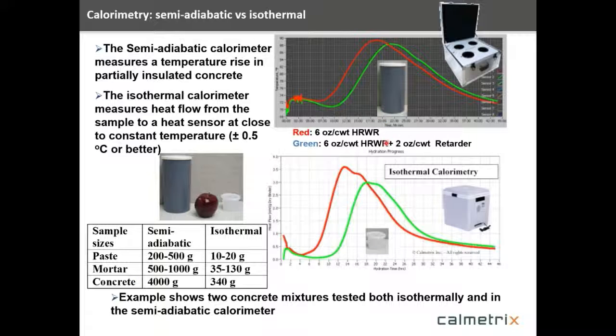Here is an illustration of the fact that the curves look very similar, but again, we're measuring temperature as a function of time. These are qualitative devices. In the isothermal instruments, we're measuring power. We can integrate under those curves and calculate energy or heat associated with the reaction. So while the curves may look similar, this is a qualitative device, this is a quantitative device, we can do quite a bit more with the isothermal devices. You can almost look at the semi-adiabatic as a subset of these. Everything that we can do on the semi-adiabatic, we can do on the isothermal, but that's not true in reverse. In other words, we can do a lot of things on the isothermal devices that we can't do from an application standpoint on the semi-adiabatic.